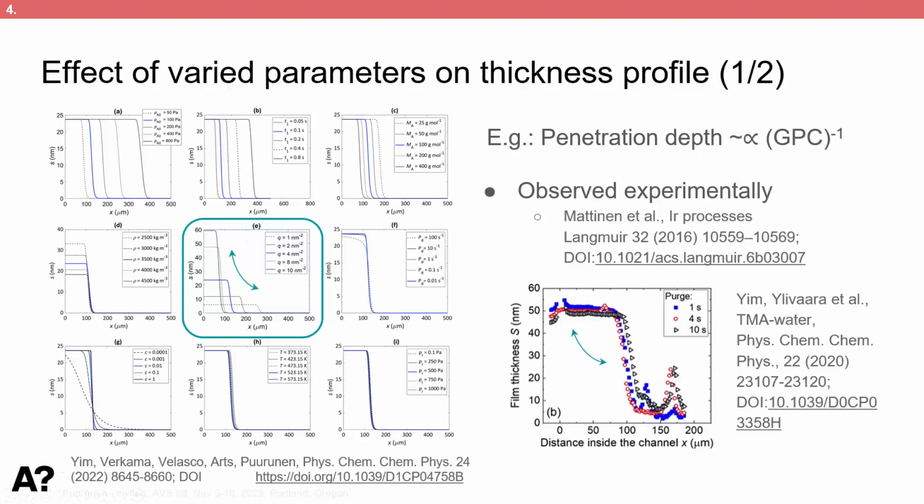And while I know that to many it's not intuitive right away, I've heard from now 3 very, very respected people in the field who say that, oh, it's not intuitive, they don't understand. But when you think it through, it actually is pretty understandable. So you have the same number of molecules coming in, and if the adsorption capacity is higher, then those do not manage to get so far into the structure before they are adsorbed. And it does lead to a higher total amount, but a smaller penetration depth.